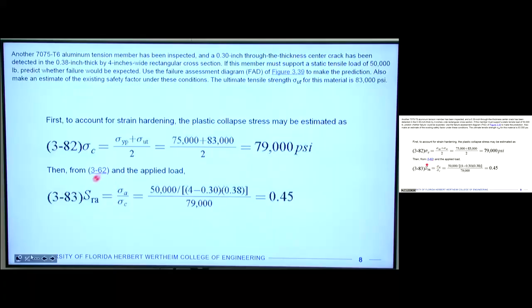And then we want to calculate the normalized load, which is the stress we apply compared to the plastic collapse stress. We just calculated that, so that's our denominator. The applied stress is the applied load, 50,000 pounds, divided by the cross-sectional area, which is the thickness, 0.38, times the width, 4, minus the crack length. We're assuming the load is carried outside of the crack. If we do that calculation, we come up with a ratio of 0.45.